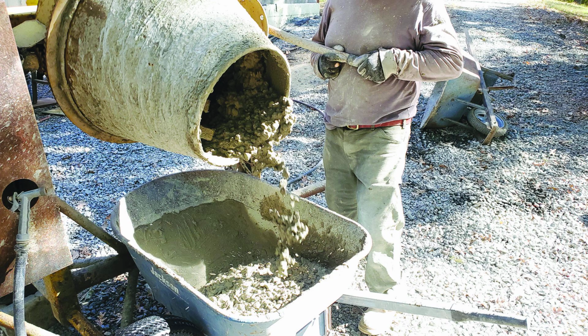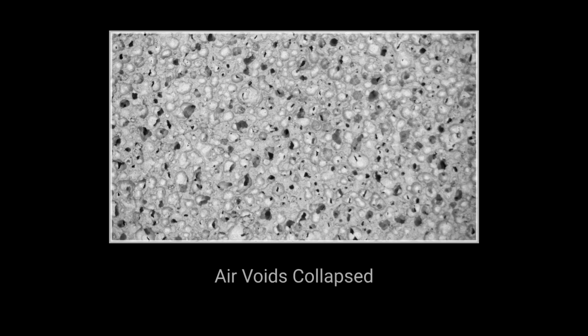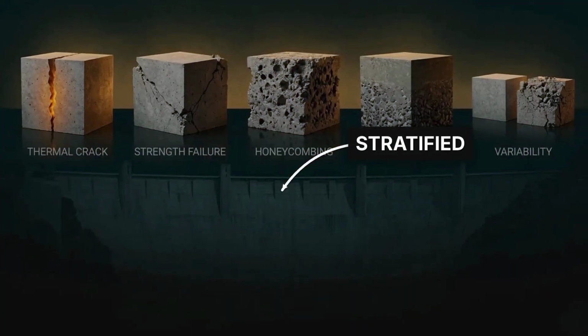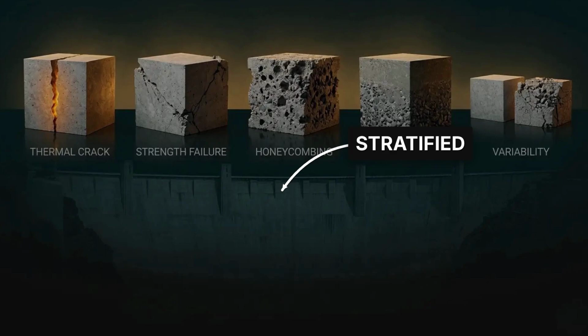The early transit mixers helped, but they introduced a new problem. Nobody had fully quantified the hydration clock. Early trucks sometimes arrived at job sites with overmixed concrete. Too many drum revolutions had collapsed the air content in the mix and weakened the final product. Others arrived with concrete that had partially stratified inside the drum.